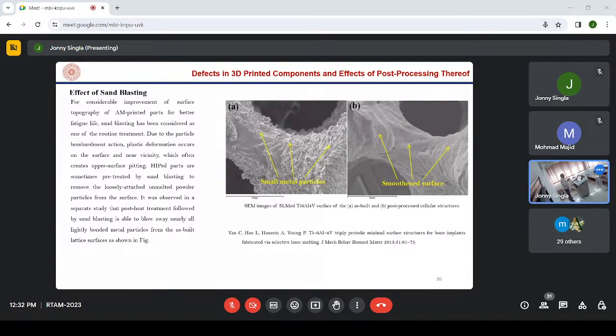Then effect of sandblasting. Sandblasting, as the name suggests, is a high-pressure sand treatment carried out on the surface. It is just to remove the loosely bonded particles on the component. In as-built conditions, this type of surface morphology is there on the material. And when you carry out sandblasting, these loose particles are removed. Right? The purpose of removing the loose particles is that they should not act as a source for crack initiation. That means they act as discontinuities. Those surface discontinuities are removed.